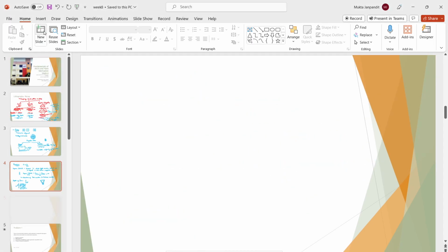Okay, I'll just add another slide. Just a little more on the recap. Another parameter was linearity. So this is just simple. The PR dimension should scale linearly with the mask dimension. So the PR width that I get after development should be linearly proportional to the mask width that I am giving. Otherwise the design that is transferred from the mask to the photoresist will not be what we expect, right? Okay.